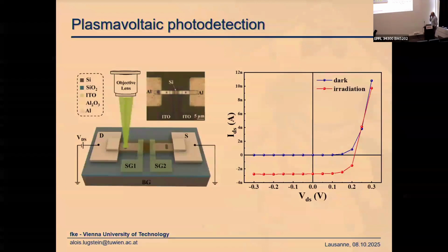And then he wanted to get control over the two barriers individually, and he made two contacts directly on top of the interfaces. And with that, he can emulate the PN junction. And if you have this device without any excitation, it indeed behaves like a diode. And if you shine light on the coupler, again, plasmons are propagating, they decay. Now you can control if you inject electrons or holes. And you see exactly what you expect for a photovoltaic device, but now it's not that you harvest light, but you harvest the plasmons. That's in principle what we would like to call a plasmavoltaic device.